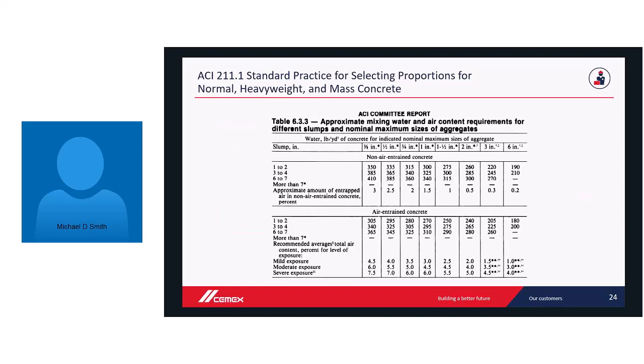So in the document, the ACI has several tables that give you generalized information about where to start with your design. In this case, this table refers to the aggregate size that you chose, whether it's a 1-inch maximum, and then what type of slump you're targeting. So in this case, if we wanted a 1-inch mix at a 3 to 4-inch slump, it recommends that you start with 325 pounds of water. Now, again, if you have an exposure situation, mild, moderate, or severe, you're going to have to increase your air content, add in air entrainment, and bump up the air. And that's going to reduce the amount of water you need in the mix, because as I mentioned earlier, adding air entrainment into your mix adds some fluidity. All those little bubbles act like little ball bearings, give you some fluidity, so you don't need as much water in your mix design. So this gives you a starting point.